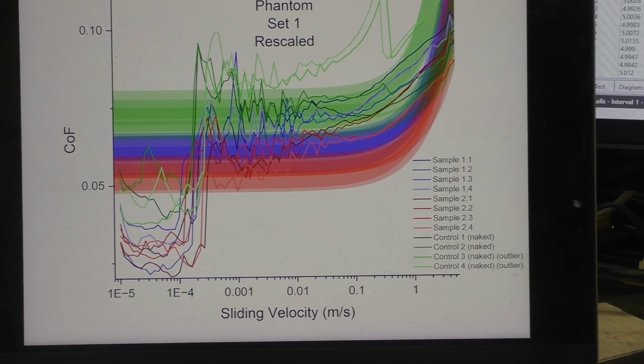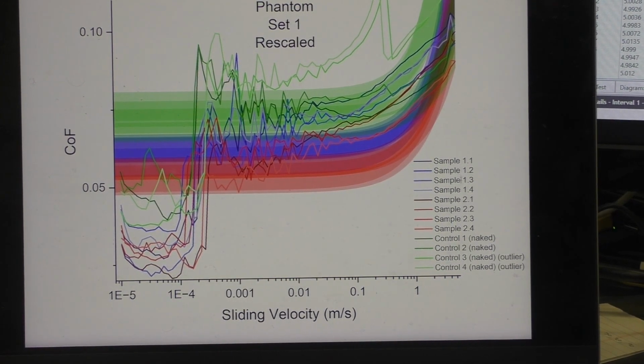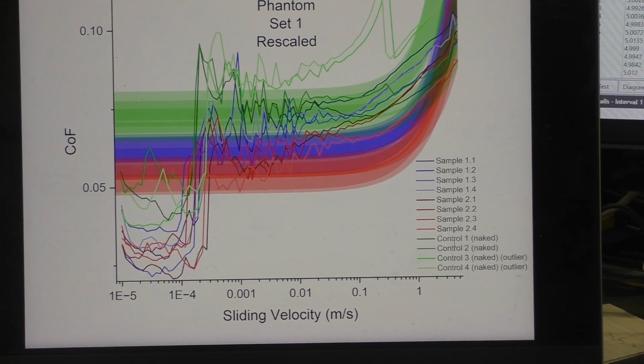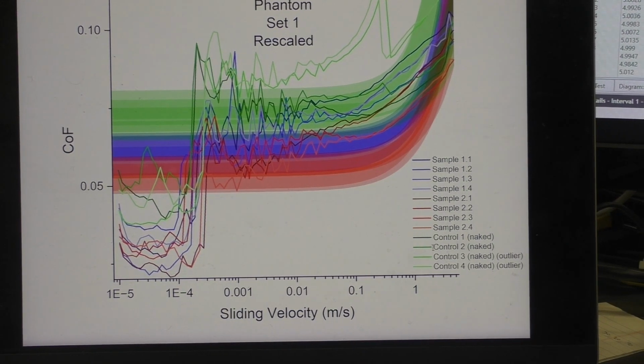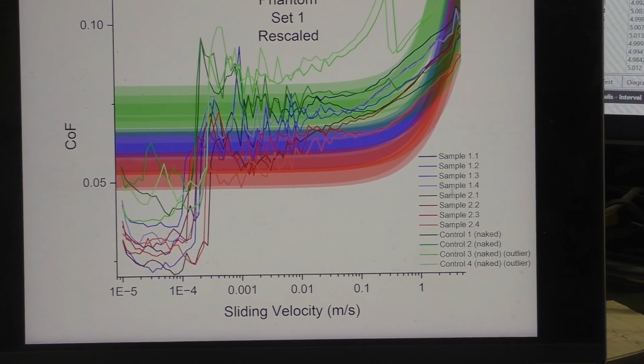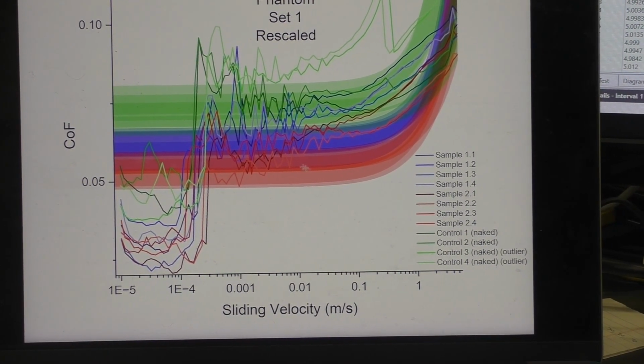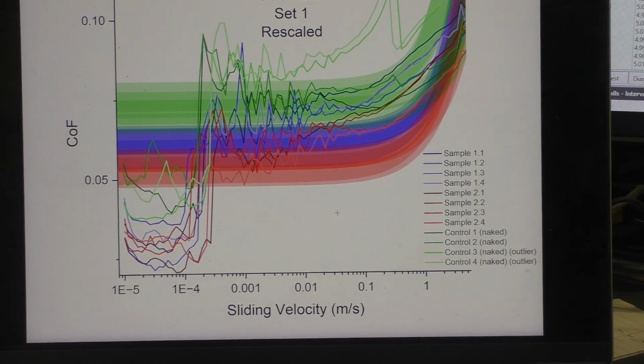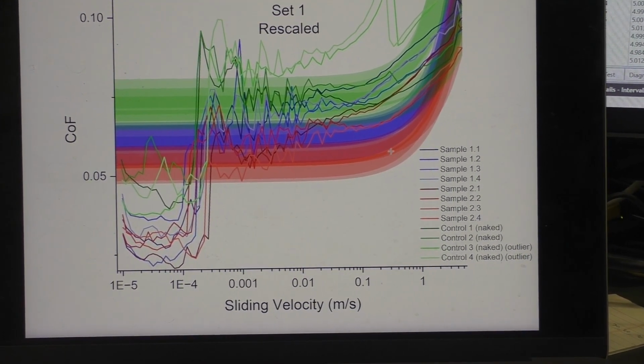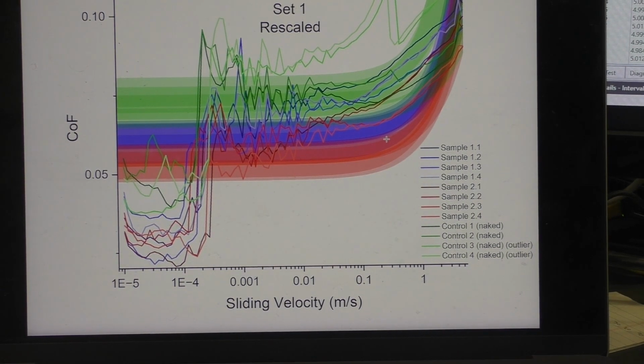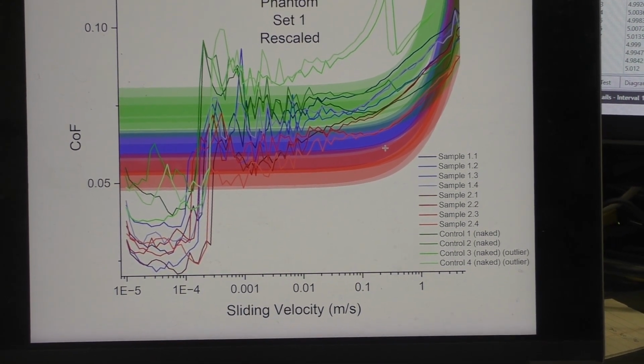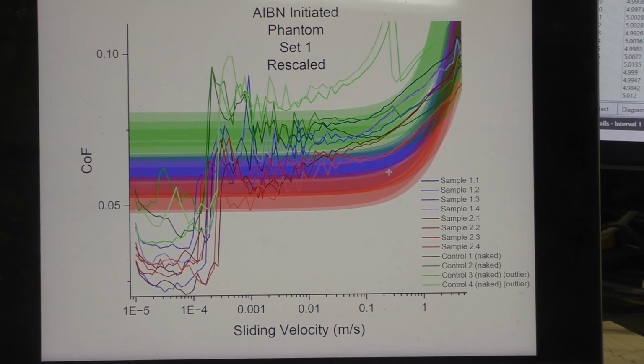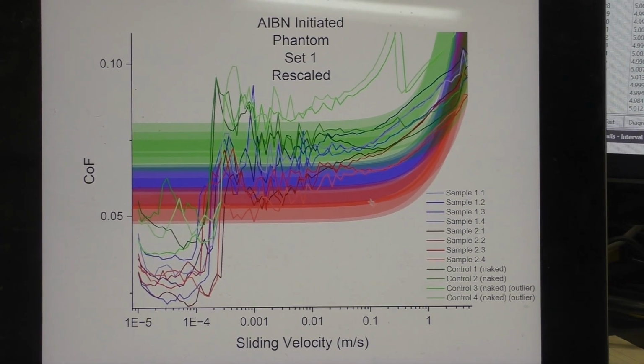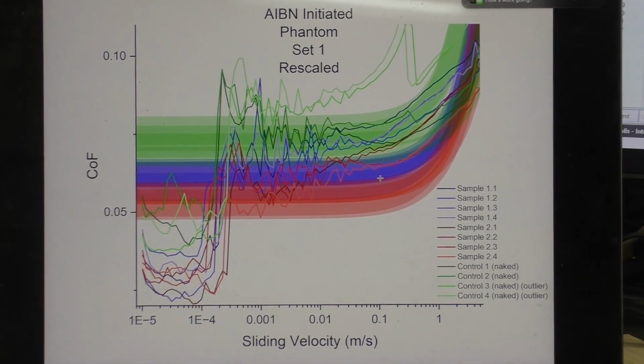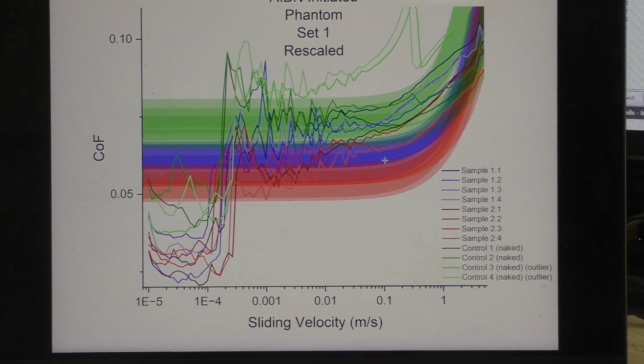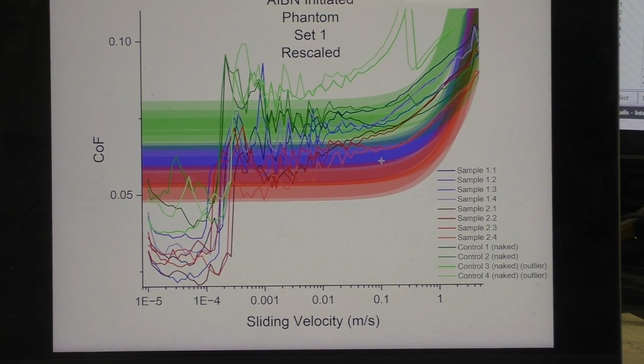As you can see here, there are 3 different samples. Sample 1 in blue, sample 2 in red, and a control sample, which is a naked ski base, in green. Because the red sample, sample 2, had the lowest coefficient of friction versus sliding velocity, especially at the higher velocities, more indicative of actual skiing speeds, we can tell that that is the highest performer. Additionally, the red, blue, and green error bars are shown to help us better distinguish the trends in the data.